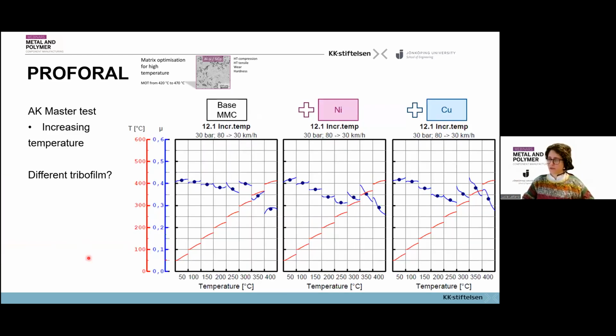So if we look into the results with increasing temperature for our materials, we see directly a different behavior with increasing temperature. The base material had somehow a constant coefficient of friction with then a sudden decrease above 300 Celsius degrees in temperature. The two experimental materials instead have a decrease that starts much earlier. We go to a valley here at around 250 degrees, but then the performance goes back up, and at the end we end with a slightly higher coefficient of friction for the material added with nickel and added with both nickel and copper. You see that the end point is slightly higher than what we had for the reference material.